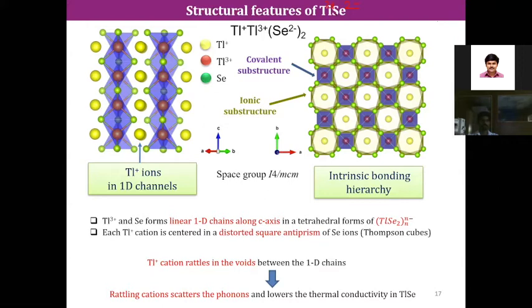And then if you draw the potential energy curve for each atom, you can see this thallium plus 1, which is blue, sits in a very flat potential well. That means it has a weaker force constant, so it can rattle and give rise to low energy optical phonon, which can scatter acoustic phonon and give rise to ultra low thermal conductivity. Now you can ask me a question: how do we make sure that thallium is actually rattling?